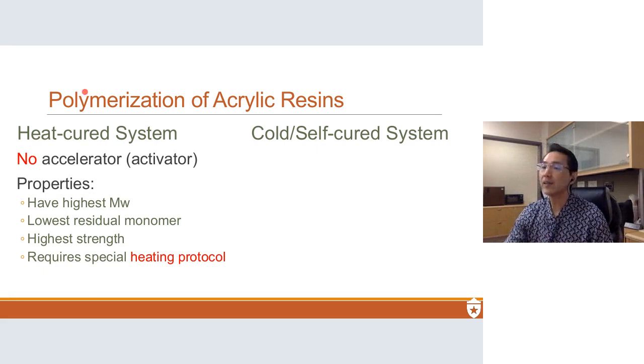The reason this is so widely used is because the heat-cured materials tend to have the highest molecular weight and consequently the lowest residual monomer, and that leads to the highest strength. However, it does require a special heating protocol. Now, cold cure resins, or self-cured or chemically cured resins, do exist, and they're really a lot more for repair materials.